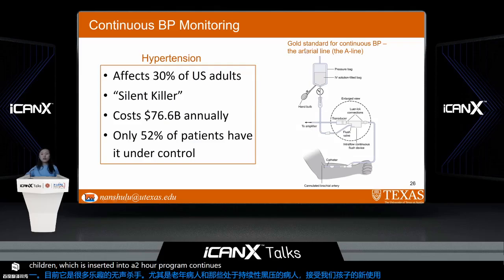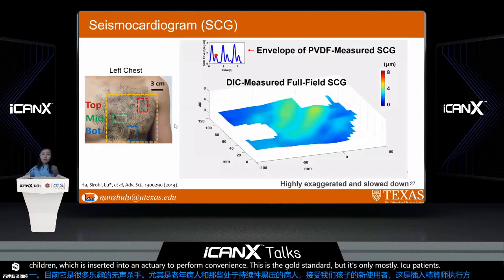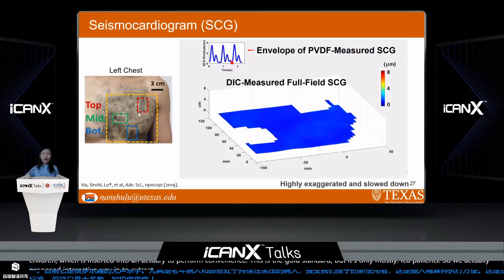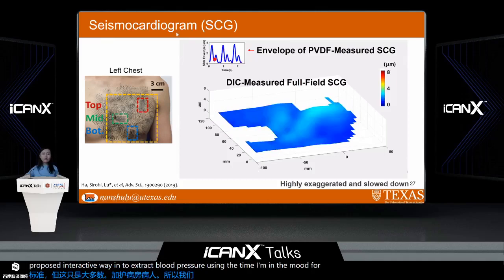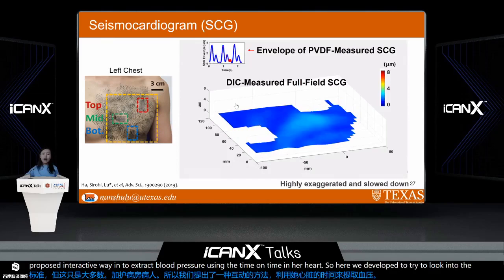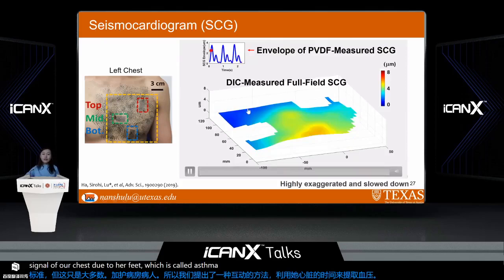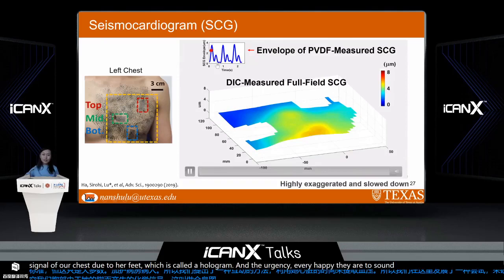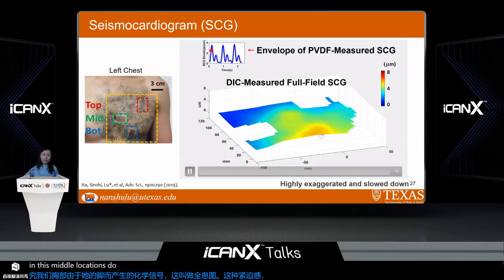So we actually proposed an indirect way to extract blood pressure using the cardiac time interval of the heart. So here we tried to look into the mechanical signal of our chest due to heartbeat, which is called a seismocardiogram. And we can see at every heartbeat, there are two sounds or two vibration peaks. And through this digital image correlation study, we found that only at this middle location, we're able to measure both very clearly.